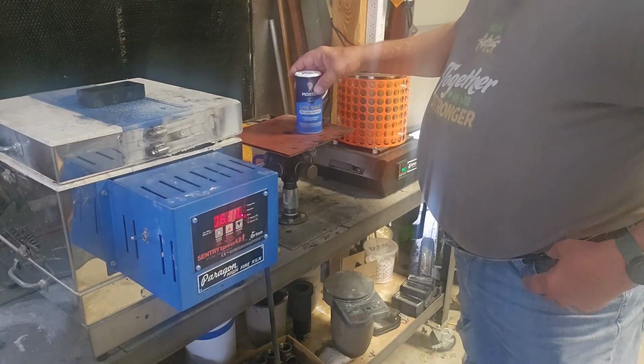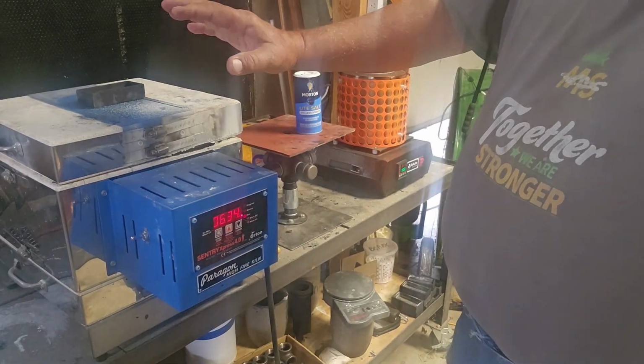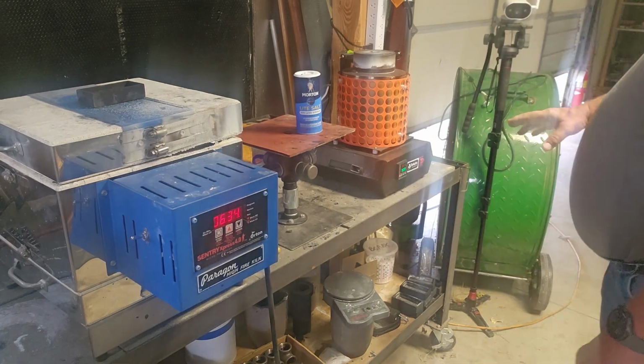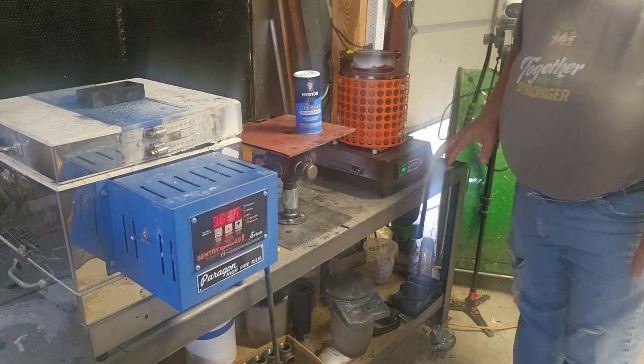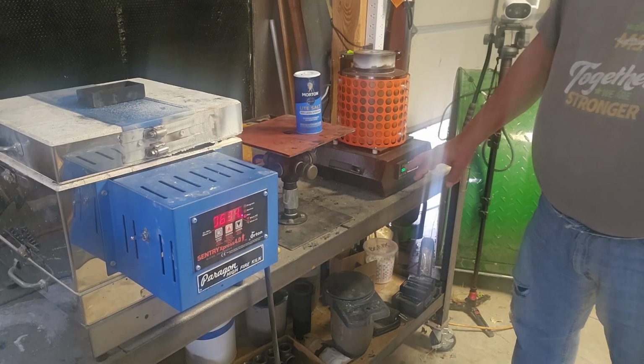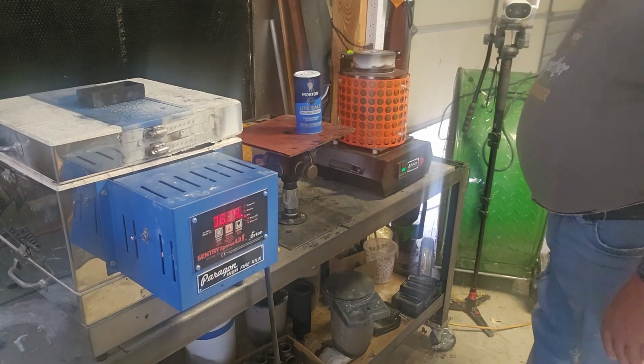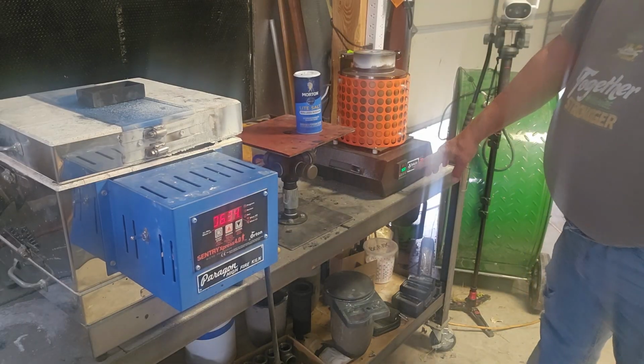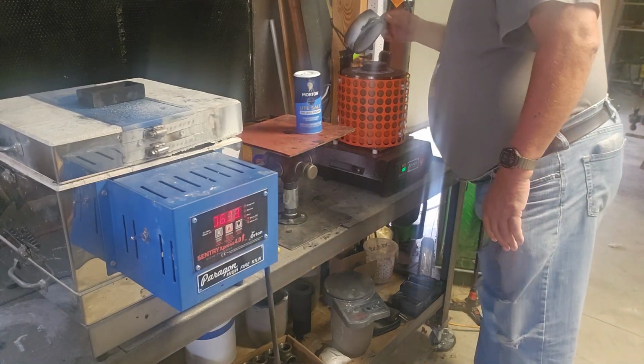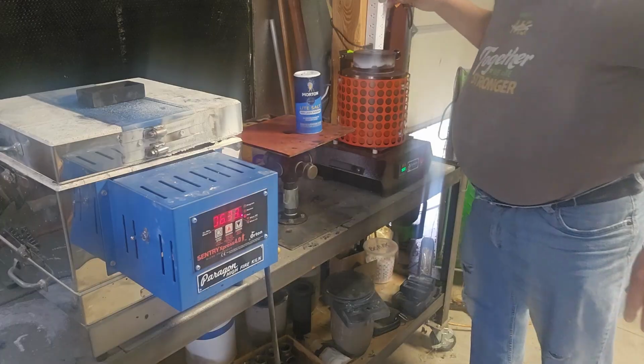Okay, we're getting closer here. The aluminum's not melted yet, but just a reminder, this mold is preheated to 500C. This furnace is set to 900C, although it's measured outside the crucible, so inside the crucible it's not quite that warm. Right now it's up to 857, so we're getting close. The aluminum hasn't quite melted yet, but it won't be too long.